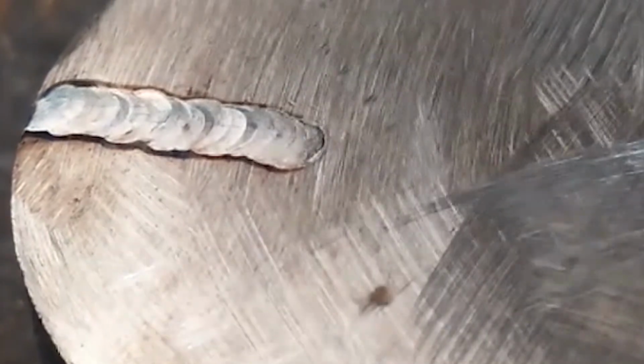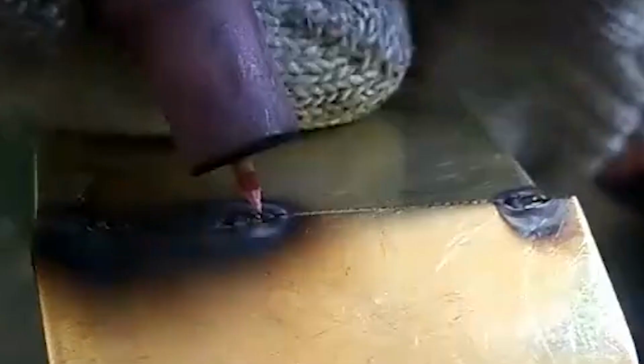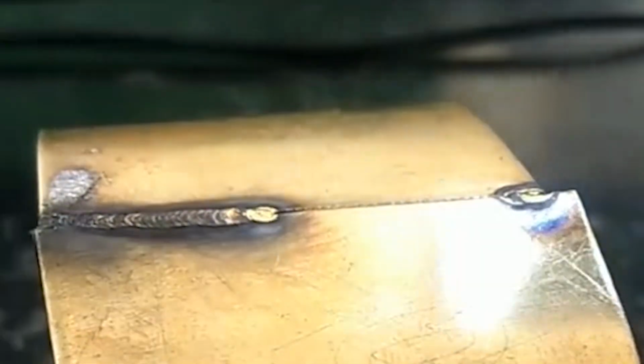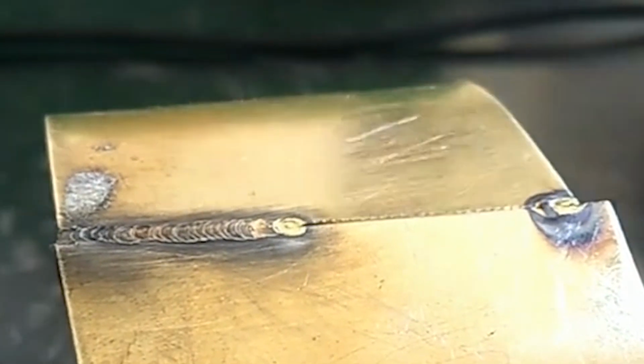The cold welding machine also uses tungsten electrodes to generate high temperature to form welding. Unlike argon arc welding, the cold welding machine uses high capacity capacitors to store energy and then controls the high speed pulse through the numerical control board. The instantaneous discharge speed reaches 10 milliseconds. The affected area is very small, there is no heat accumulation, and the solder joints can be bright and not deformed, so the cold welding effect can be achieved. Weldable materials: stainless steel whiteboard, stainless steel pipe, color plate, galvanized material, iron plate, brass copper, aluminum plate, aluminum profile, titanium alloy, etc., various mold steels.